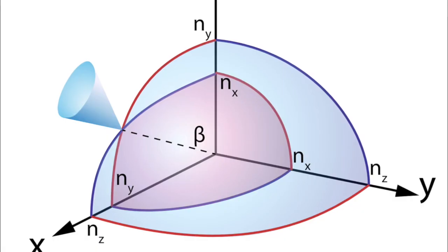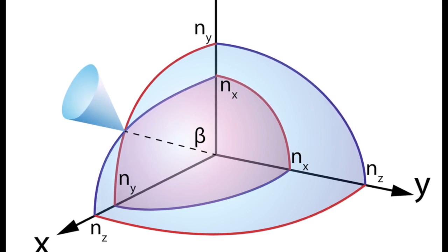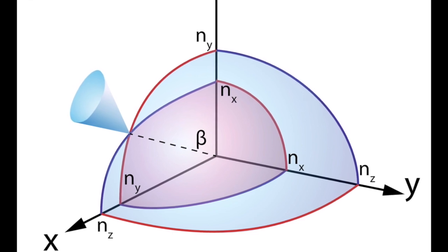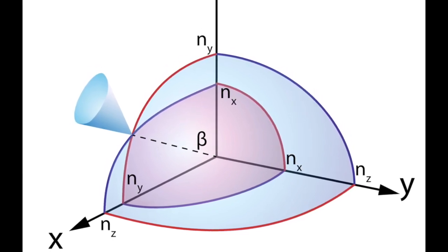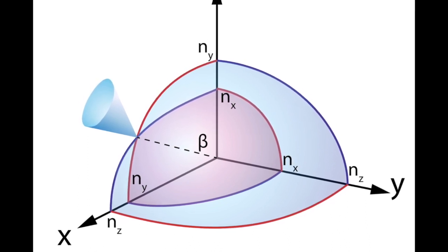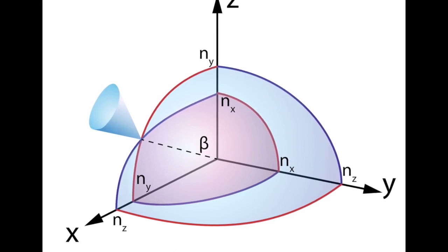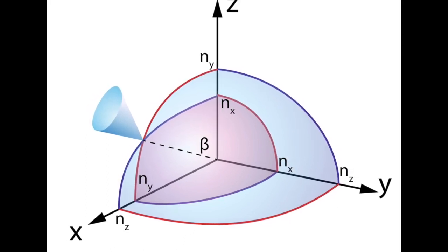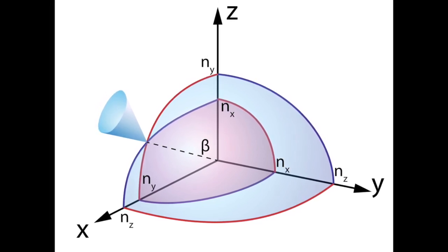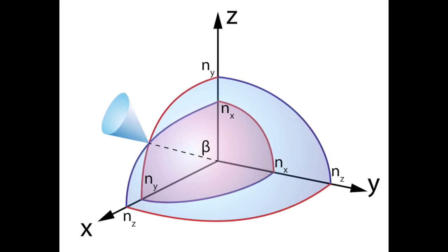Finally, what about when all three axes are different lengths? We'd be dealing with a biaxial crystal in that case, with 3 indices of refraction. Our ellipsoid would look like a flattened football. It's a more complex situation, so all we'll say about it is that biaxial crystals with good optical properties are hard to come by, and that the great Irish mathematician Sir William Rowan Hamilton figured out, without the use of experiment, that the resulting beam would not be some sort of triple refraction, but a cone of refracted light.